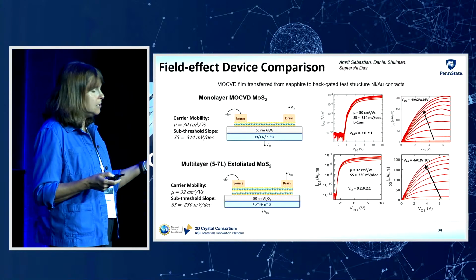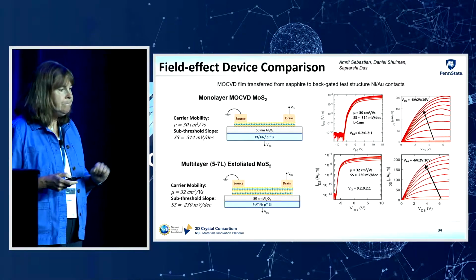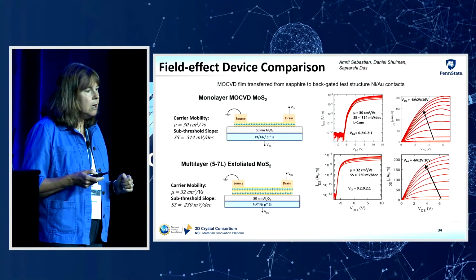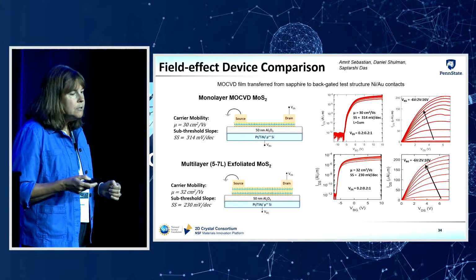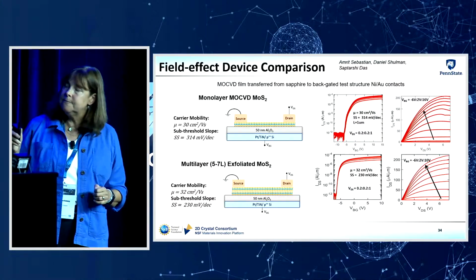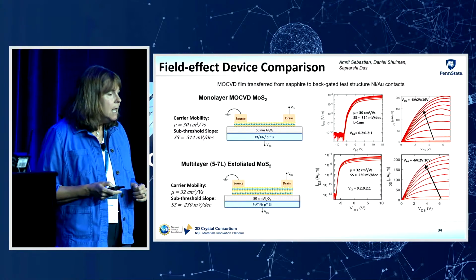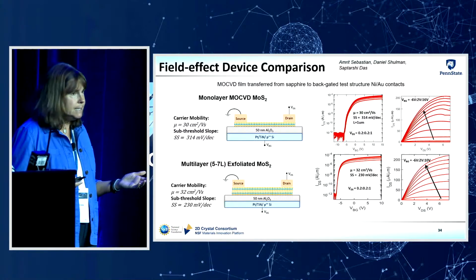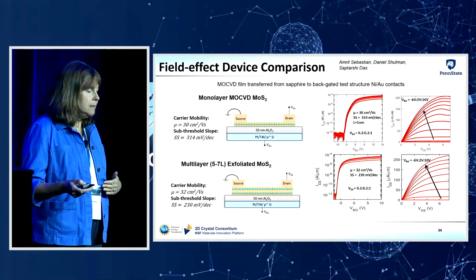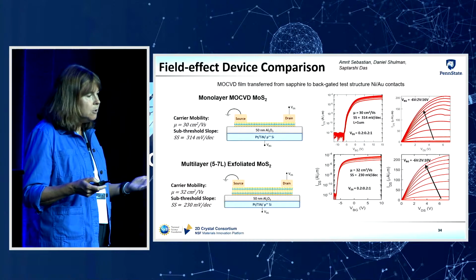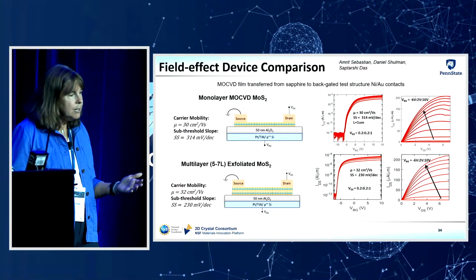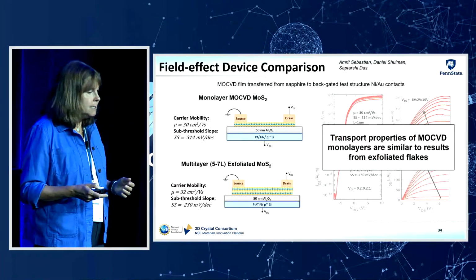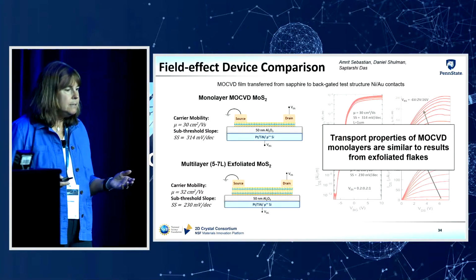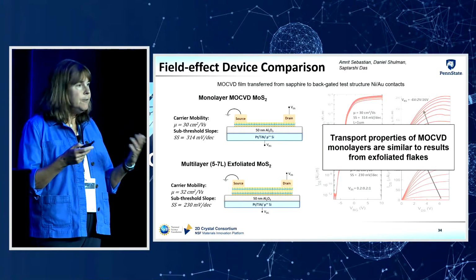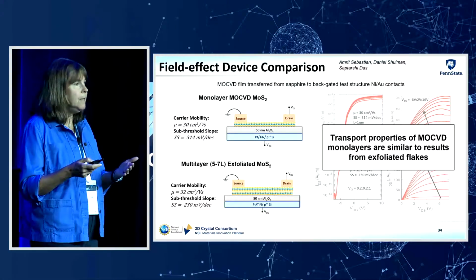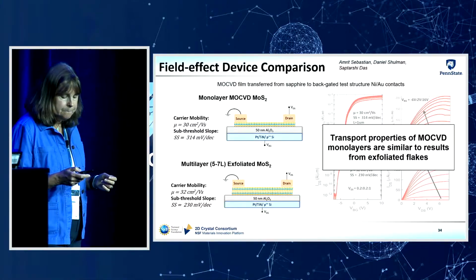So these are films that are exfoliated from a bulk crystal, right? And I should mention, this is some work done by my colleague Saptarshi Das at Penn State. So they compared the transport properties of the two different types of molybdenum disulfide. And what they found is that the carrier mobility was very similar for the MOCVD film and the transistor fabricated using the exfoliated molybdenum disulfide, similar subthreshold slope, and other characteristics. So the upshot is that the transport properties of the MOCVD grown monolayers are very similar to what you would get from exfoliated flakes, which is sort of the benchmark right now in the field.